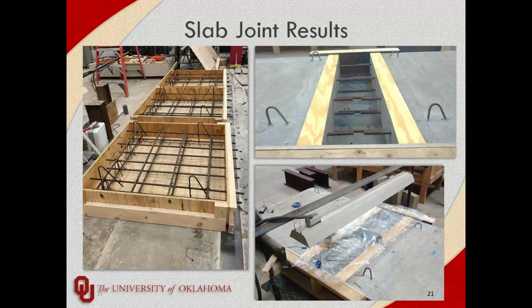And we would cast these 4x4 decks with some bars sticking out. The bars stuck out about 5 inches or 8 inches or so. And then we would tie them together with a very short lap bar in the center, as you can see in the upper right. This equates to approximately an 8 db splice length, which is a common recommendation for Ductal UHPC because it has such high strength, and the addition of steel fibers helps really increase the bond strength and really reduce that development length.